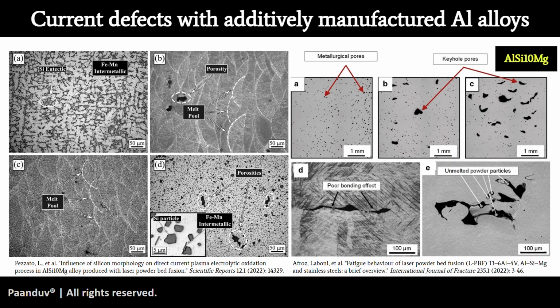Talking a little bit more about these defects, specifically for AlSi10Mg, which is one of the alloys of interest for today's talk. There are many porosity and poor melt pool dynamics related defects. There could be metallurgical pores, there could be keyhole pores, there could be a lot of unmelted powder particles, poor bonding effect, and you name it, basically every defect that you encounter in additive manufacturing in general, the same sort of entire gamut of those defects can again be seen when it comes to AlSi10Mg alloy, which has a lot of applications in aerospace and defense, but it also comes with its own set of defects.